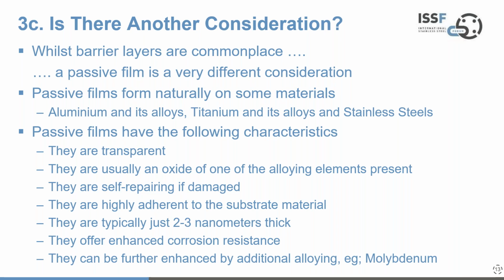They are self-repairing, an important feature if they're damaged. They are highly adherent to the substrate material. And that's generally because the molecular size of the oxide is very close to the molecular size of the substrate material. So you get a lovely bond there. They're very thin, typically 2 to 3 nanometers thick. And they, as a result of that, offer enhanced corrosion resistance.